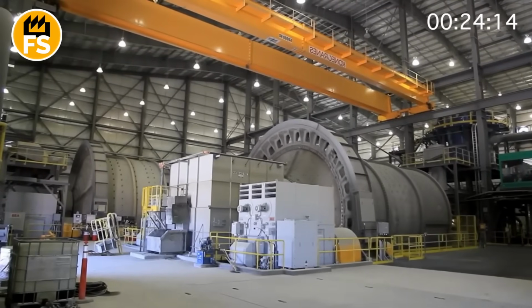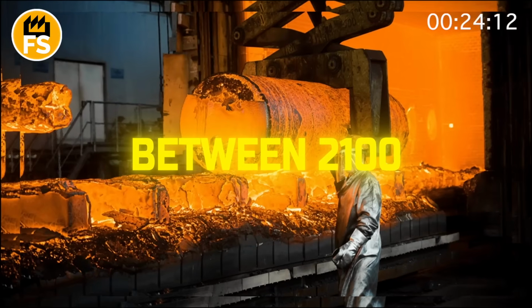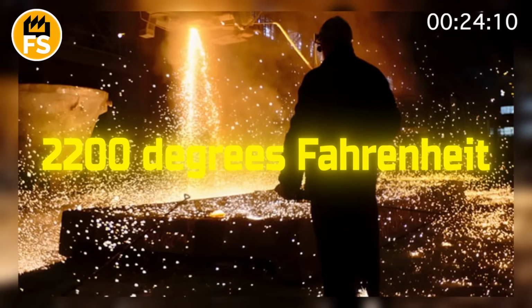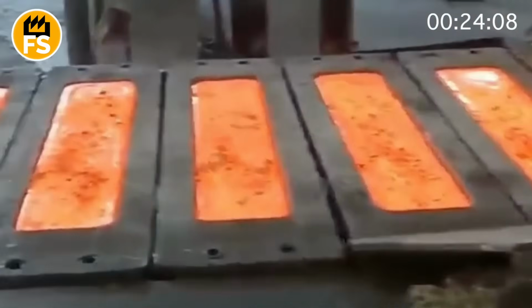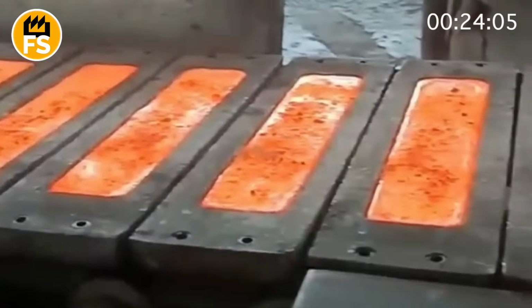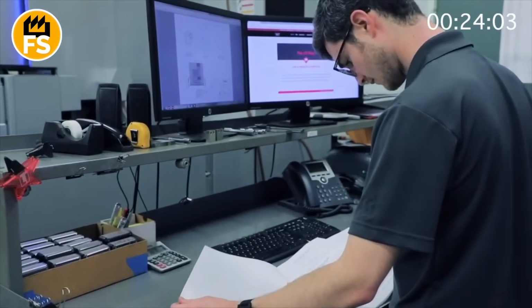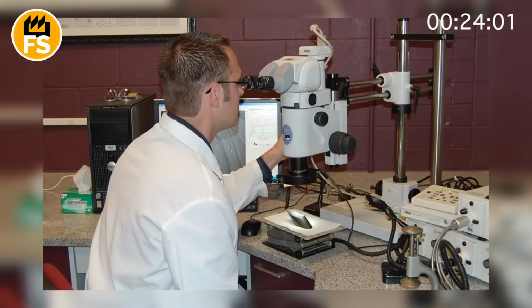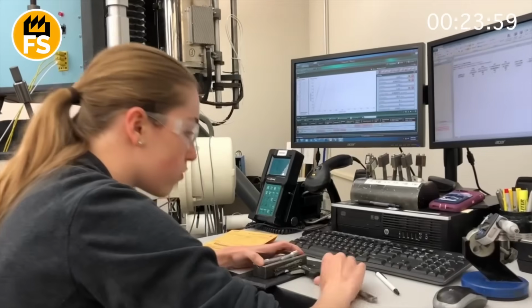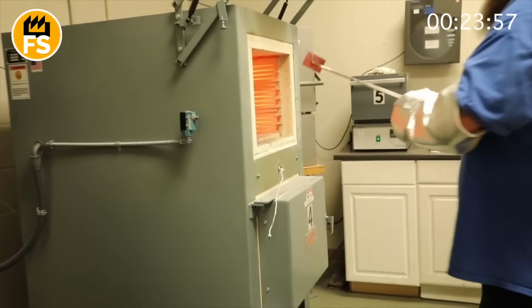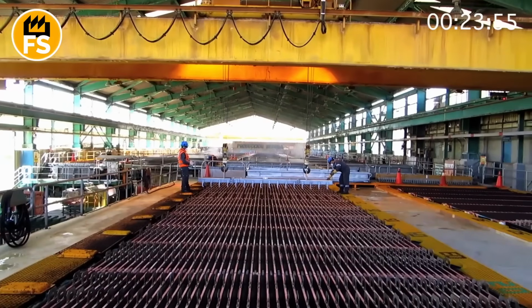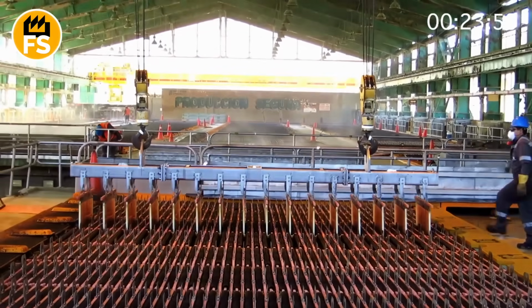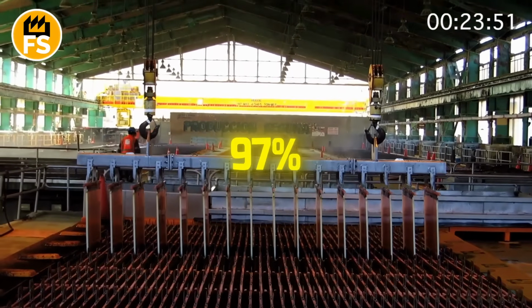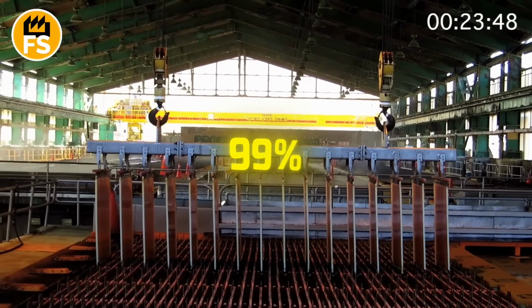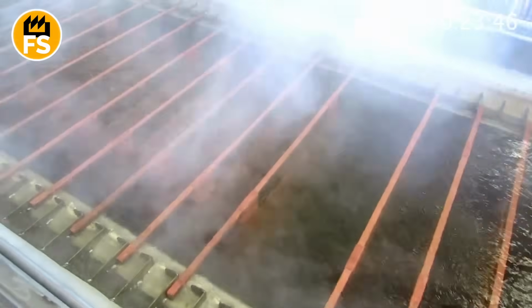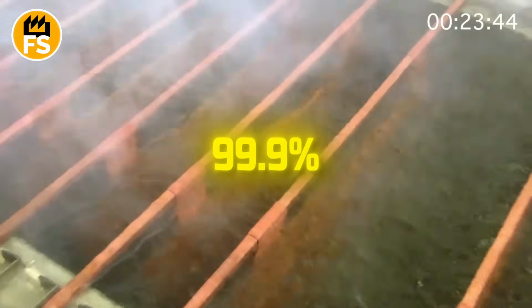The temperature is strictly controlled between 2100 and 2200 degrees Fahrenheit, and the current strength is regulated with an accuracy of tenths of an ampere. Laboratory analyses are conducted every 30 minutes. Chemists check the metal's composition, tracking how the amount of impurities decreases. Gradually, the purity of the copper increases: 95%, 97, 98, 99. And finally, the coveted mark of 99.9% is reached.